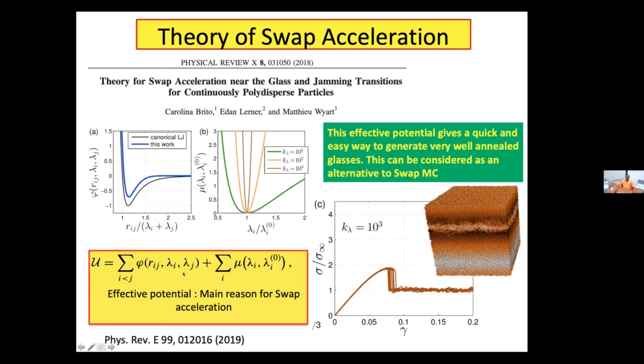This potential has two parts. One is the usual pairwise interactions, and there is also a potential coming from size fluctuations. The size fluctuations here are taken as a kind of harmonic potential. And if you take this effective potential and do a gradient minimization to generate the glass state, then you are going to get these ultra stable glasses.